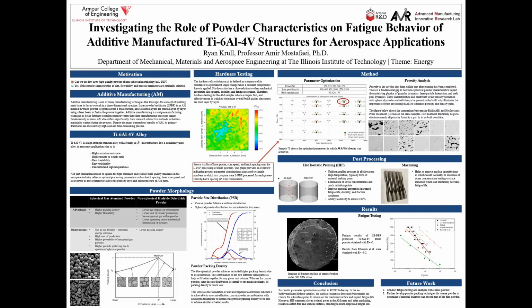The reason this has been so common is due to two main advantages. One being the ability to have higher packing density, which I will discuss more in depth later on, but also due to its higher flowability. However, additive manufacturing is seen as a high-cost method compared to other techniques, and rightfully so, as fine spherical powders are very, very expensive. This is why additive manufacturing has been reserved mainly for lower production type processes. Spherical powder is more expensive due to its high production costs, and this correlates to the production of spherical powder being a high energy intensive process, which is less eco-friendly as a result.